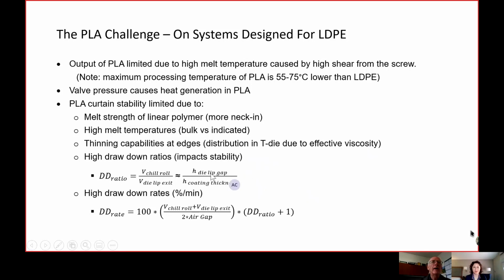In our experiment, we looked at the drawdown ratio, and this is the change in thickness of the polymer as it leaves the die lips to the final coating thickness. A more rapid change of this, or a greater change in thickness, again, affects the draw of this polymer, and with the linear polymer, it creates more neck in and instability. When we lower it down into the nip, it also draws at a higher rate of extension, and this also tends to contribute to the instability in the melt curtain.